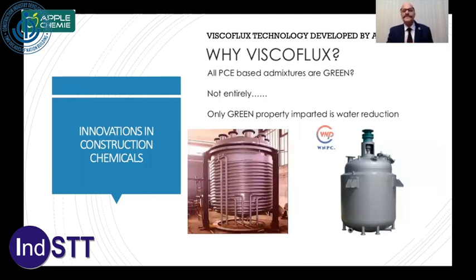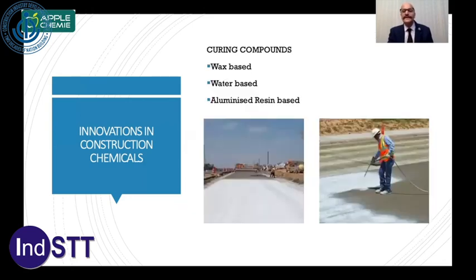The further development in the PCE technology is the Viscoflux technology. Well, I'm very proud to be a part of Viscoflux technology because this is a green technology. How green? Because basic PCE technology aims at producing a product by heating it up to 160 degrees centigrade in the first phase of reaction, and in the secondary reaction another 120 degrees centigrade is heated, then cooled, and the process takes around 10 hours. In Viscoflux technology, what you can see on the reactor on the right hand side, it is only one process. It is almost at room temperature, no heating, no cooling is required, and the process is complete in 2 hours. So that's a great innovation.